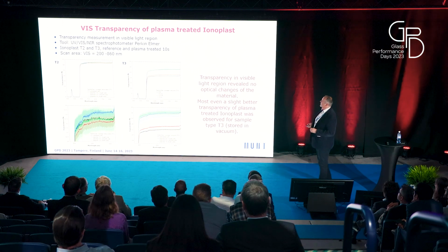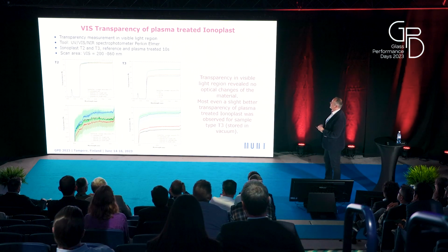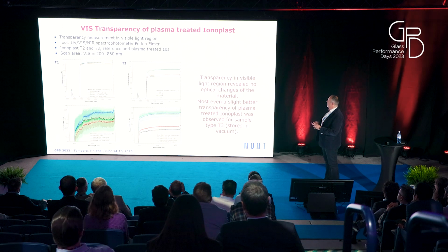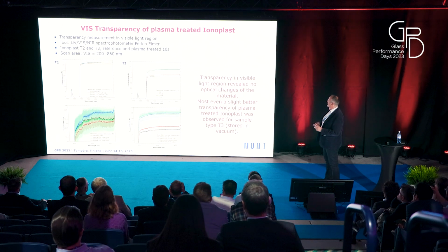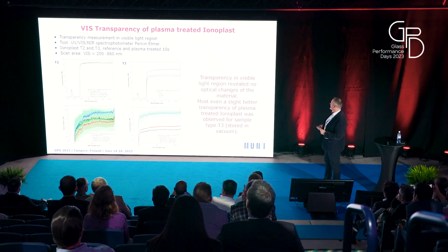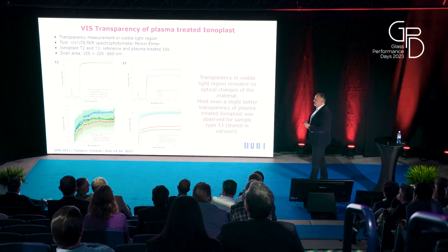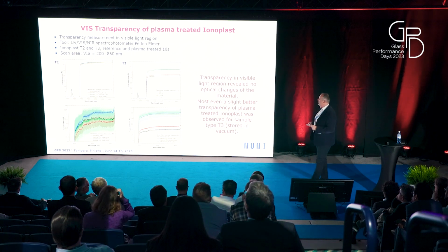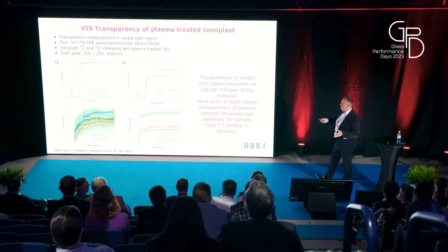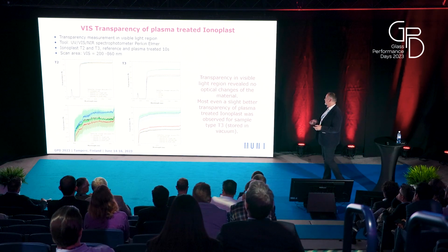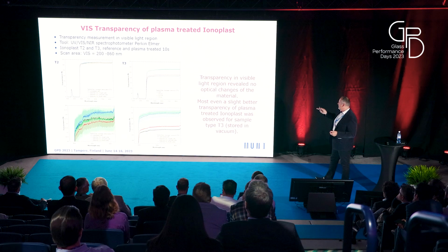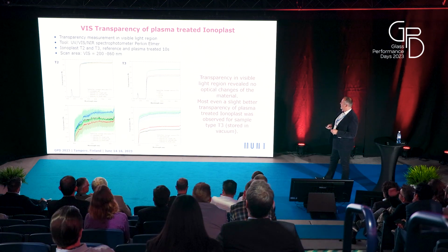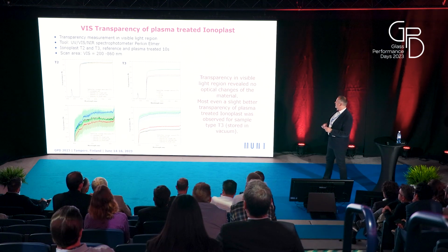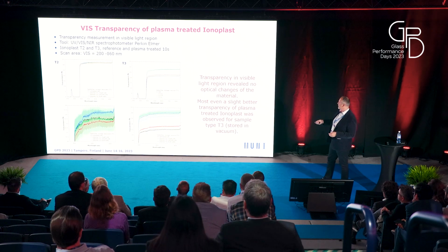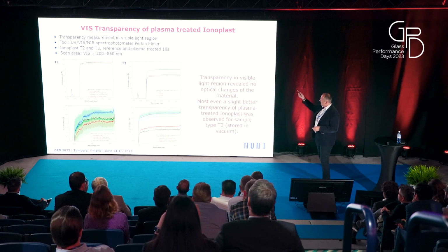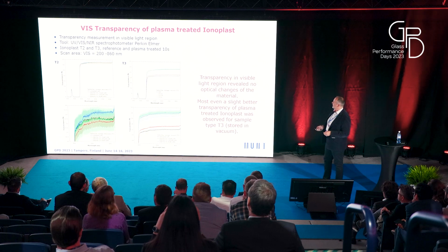We investigated also the transparency of plasma-treated Ionoplast, and in the visible light region we revealed no optical changes of the material. The company with which we collaborated also told us that this is not so important a problem in the lamination process, but we investigated it. Moreover, we observed a slightly better transparency of plasma-treated Ionoplast for the sample which was stored in vacuum, as we can see on the graphs on the right side.